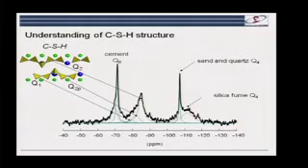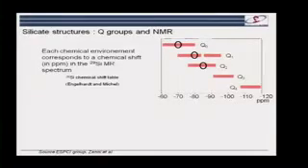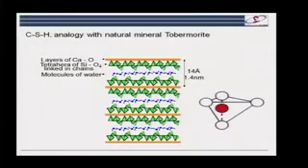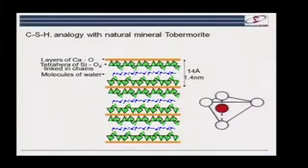You can also see this very interesting arrangement of the chains that was already visible in this diagram back here, what is called the dreierketten structure. It goes 1, 2, 3, 1, 2, 3, 1, 2, 3. Two of them are attached to the sheet, and one of them is what's called a bridging site. And it's these bridging sites that are most often missing.